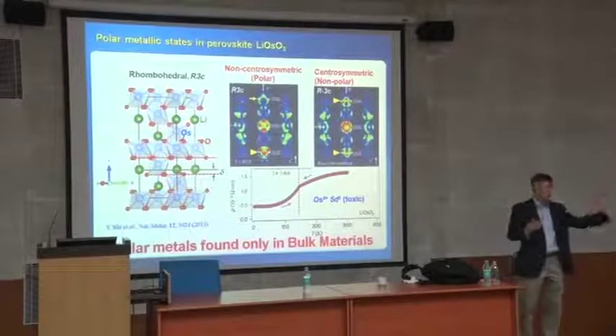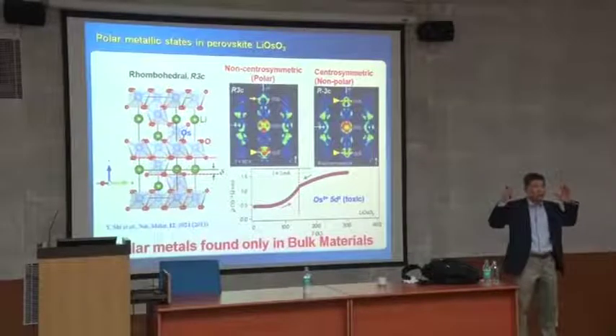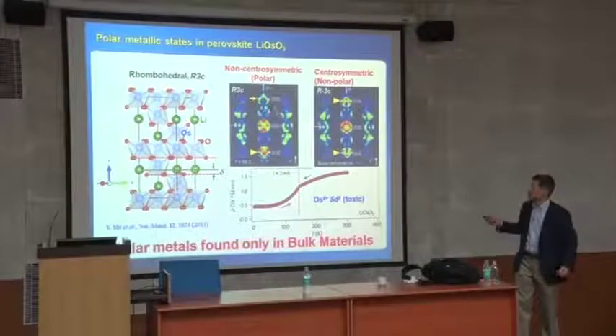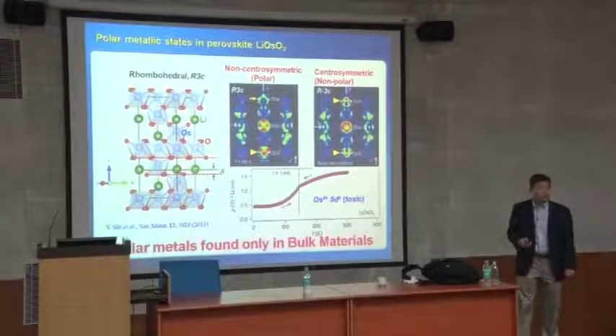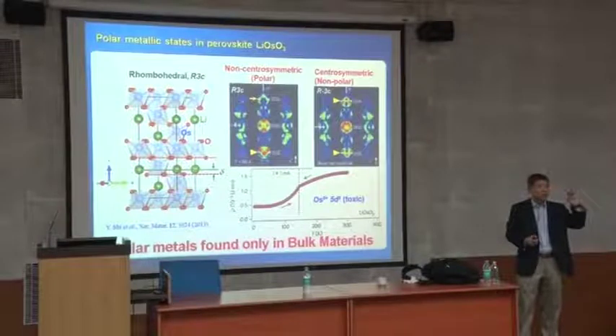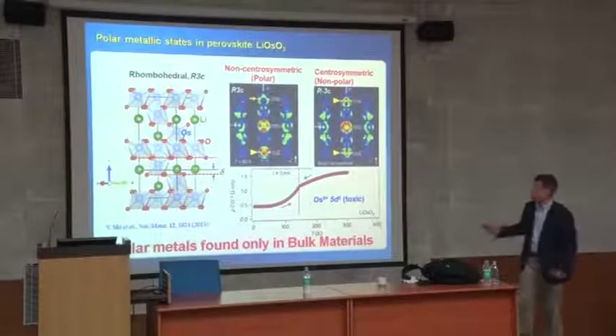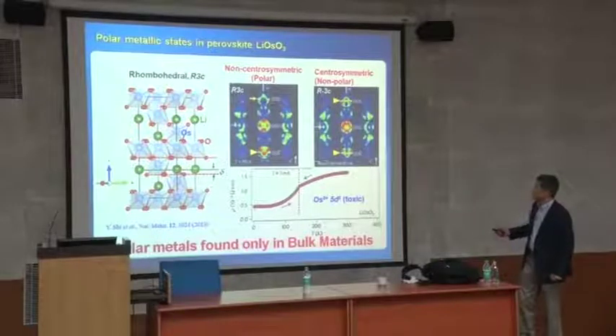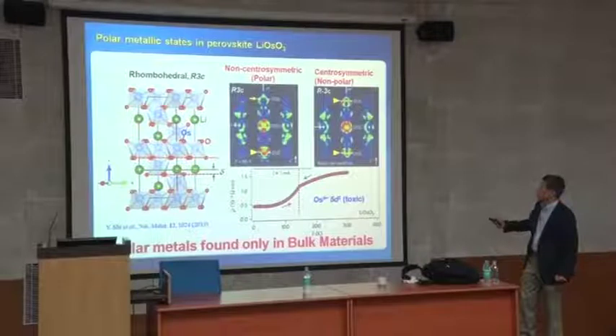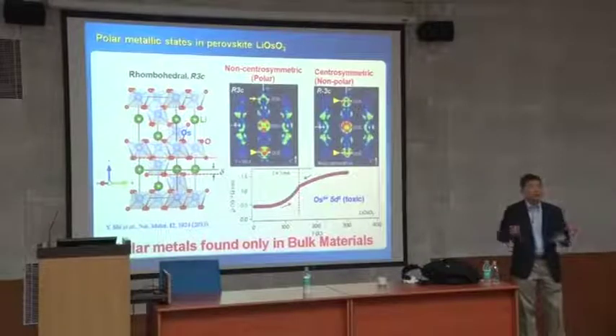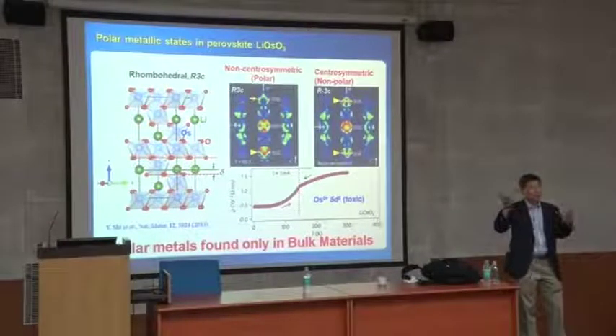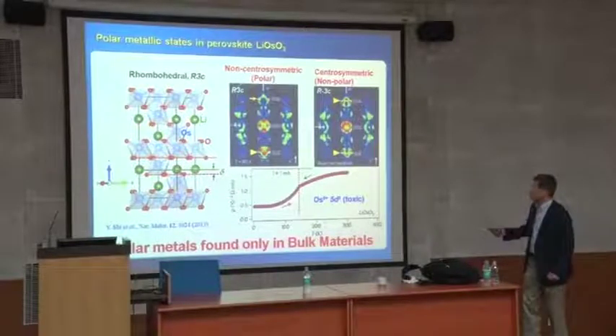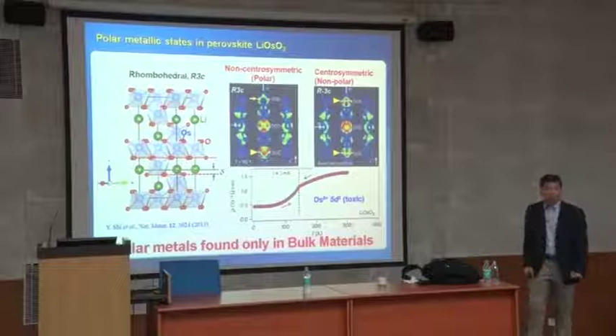That means this side and that side are exactly the same, mirror symmetric, which is why we call it centrosymmetric. But this one is not. This one and that one are different, because the atoms are not in the exact center; they are off center. Okay, that's one way you can do it. So they look at the symmetry at high temperature and low temperature, and it still maintains metallicity, but you are creating this kind of polar state in this bulk material. Okay, that's coming from a metal-insulator transition at different temperatures, and the same material forms a polar metal.